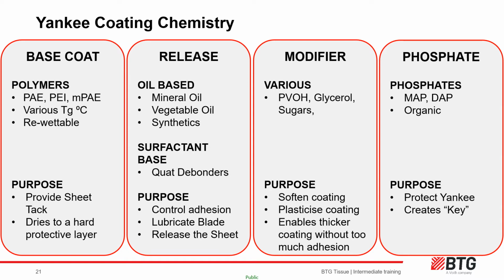Monoammonium phosphate or diammonium phosphate forms phosphate ion complexes on the Yankee surface, which passivates and protects the Yankee surface and can actually repair some small areas of localized damage. Its use is always recommended when the old coating layer has been stripped, either intentionally at a polish or a regrind, or unintentionally through a process or chemical blip. Organic phosphate chemistry is very complex, but sometimes these are used in niche applications, for example in TAD. When using phosphates, high hardness in the spray bar can lead to nozzle blockages, so there is a trade-off between having the desired amount of calcium and phosphate salts.